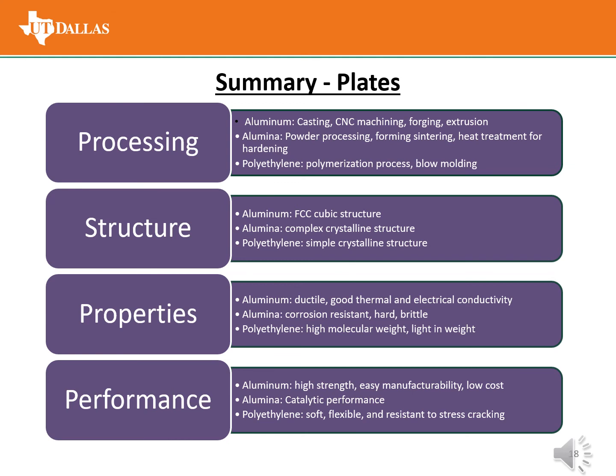In this slide, we focus on the processing, structure, properties, and performance for each of the three different materials that we have used. Now, for processing, aluminium is processed by main processes like casting, CNC machining, forging, and extrusion. While for alumina, powder processing, forming, sintering, and heat treatment for hardening are the main processes, and polymerization process and blow molding are generally used for polyethylene. Aluminium structure is FCC, face centered cubic structure. Alumina is complex crystalline and polyethylene is simple crystalline structure.